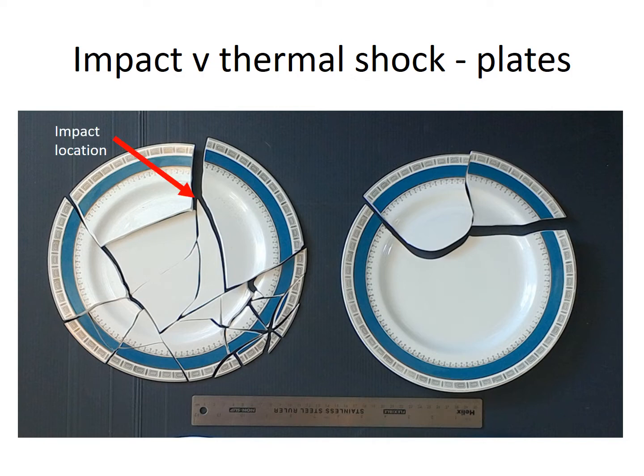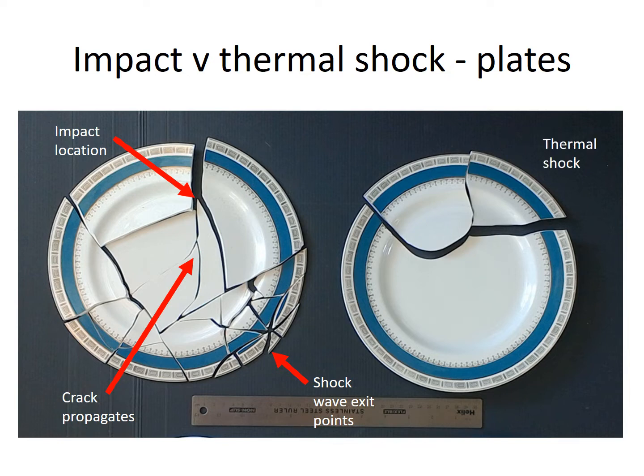The impact caused the plate on the left to crack. The crack crosses the plate, propagating into further cracks as it goes. At the point where the shock wave reaches the edge of the plate, it has produced many small sherds, and all the sherds are angular. In contrast, the plate broken by heat has broken into a few large sherds only, and the fractures are curved and wavy, and the fractures are mostly at right angles to both the surface of the plate and to its edges.